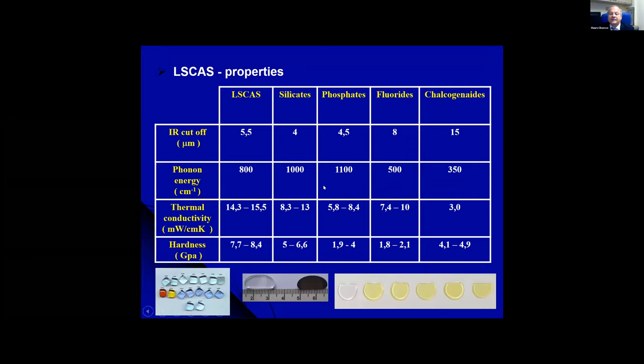There are some properties that justify why we have been studying this system for so long. If you compare this first column, phonon energy is very important when you want a material for luminescence, and the phonon energy defines the quantum efficiency, the rate of luminescence you're going to get from this material. It is intermediate between the fluorides or chalcogenide glasses, and even phosphates, and the silicates. It means the phonon energy is good, because the fluorides and chalcogenide glasses are not so strong to support some hostile environment.